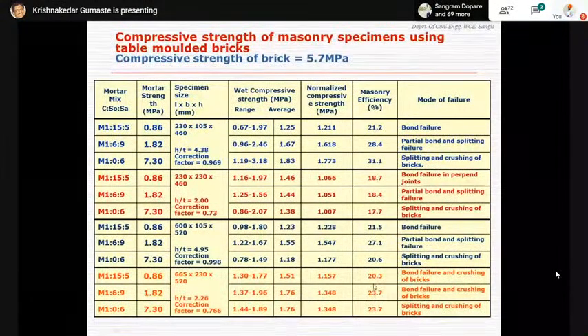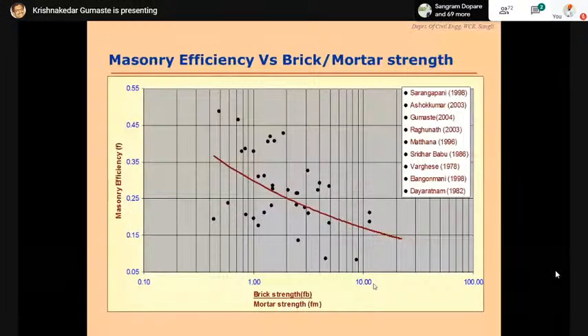So based on the various studies done by all these people, an empirical relation can be achieved based on the data of brick strength to mortar strength. If you know the strength of the brick and the strength of the mortar, the ratio of these defines the scale on the x-axis, in a semi-logarithmic nature, and the y-axis defines the masonry efficiency, that is, the wall strength relative to the brick strength, and the various points show you the best fit.